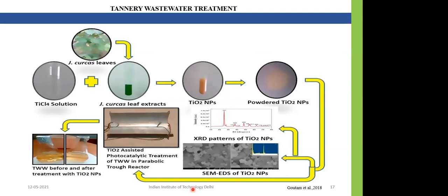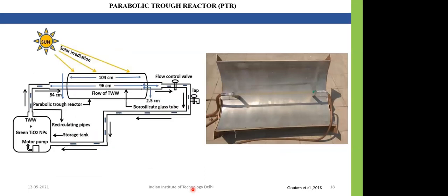So, for this particular study, they have utilized a self-designed, fabricated parabolic trough reactor (PTR), which is shown here. This PTR was constructed using stainless steel, aluminum, chrome plated, and a parabolic trough of 104 centimeter length and 84 centimeter width approximately. The rubber tubes were further joined with a completely closed plastic tank of 5 liter capacity, fitted with a submersible motor pump at the bottom to maintain the continuous circulation of the wastewater throughout the solar photocatalytic treatment process. So this is one of the pilot scale studies recently explored by Gautam et al. And they have effectively concluded that these plant-based photocatalysts can be effectively utilized for the degradation of organic contaminants.